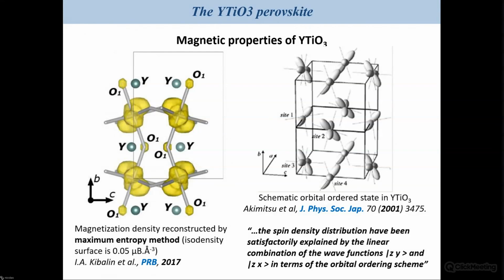In our idea, it was better to just refine jointly X-ray and polarized neutron diffraction experiment together, and at the end, consider if the spin distribution we obtain around the titanium atom will have the same shape as the one observed by our colleague in Japan. So we